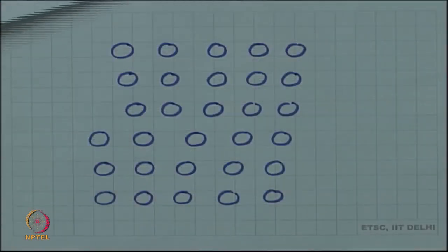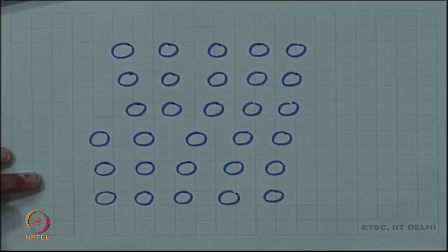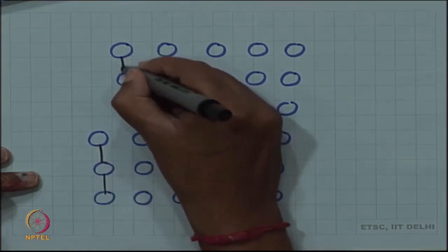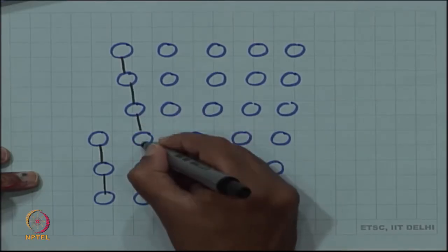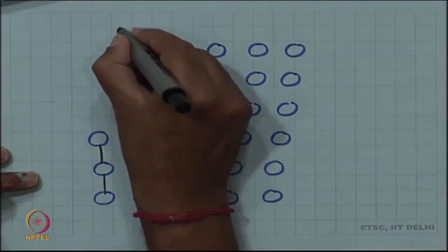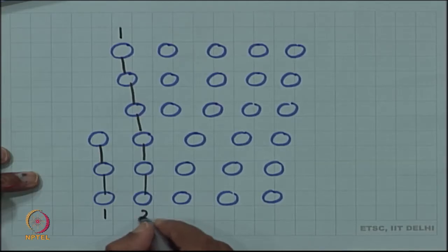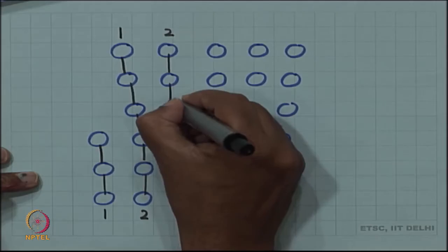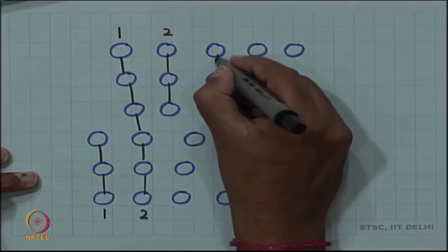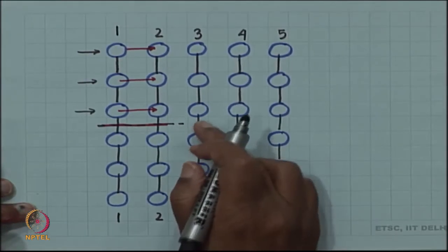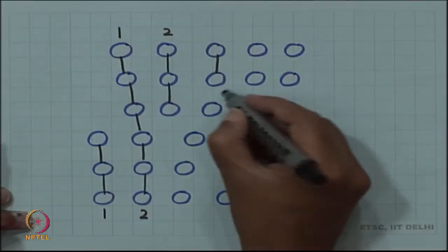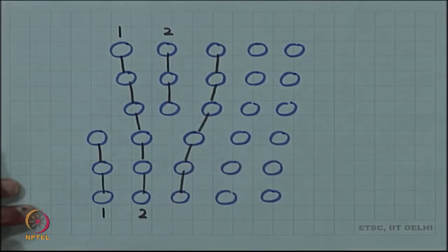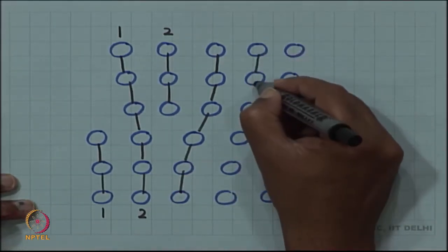So, you have already seen in your study of dislocation that since the first plane from the top is joining the second plane from the bottom, the second plane from the top is not able to join the third plane, because the third plane is continuous. Remember, I have not cut the bond there. So, the third plane just deforms to accommodate the second half plane from top.